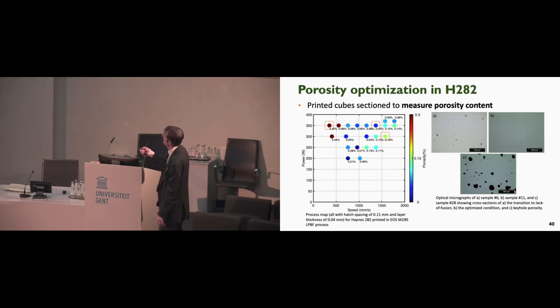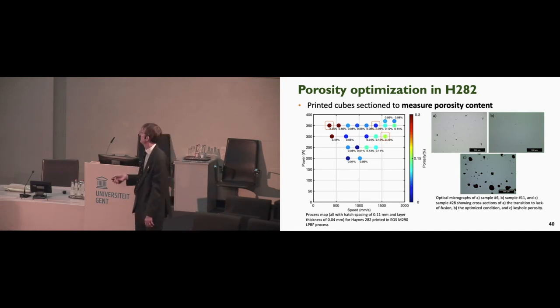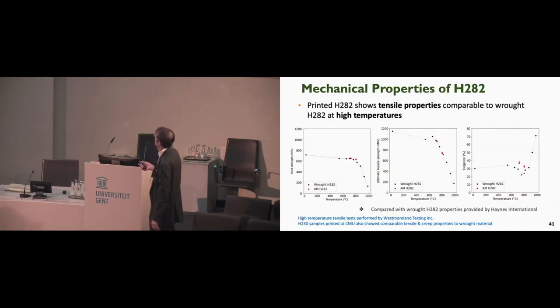In fact, interestingly, it appears to be a sort of ridge line like this. So that's telling us that we have more to learn. But you can indeed get to the point of very low porosities, as low as 0.01%. And from doing that, of course, besides printing those things, we also are testing the materials. So this is just the results of some high-temperature tensile tests. And yes, of course, we're doing creep tests as well.